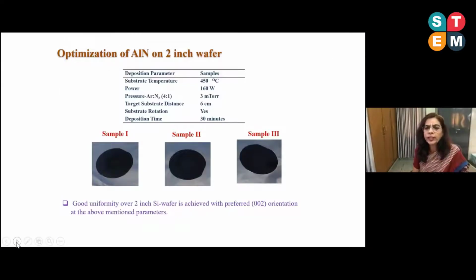These are the films deposited over the 2-inch wafer. The film seems to be very uniform, and because of the deposition constraint, we have been able to produce these films only over a 2-inch wafer. Otherwise, if we could have a bigger heater, then we can go for even the 4-inch or 6-inch geometry.